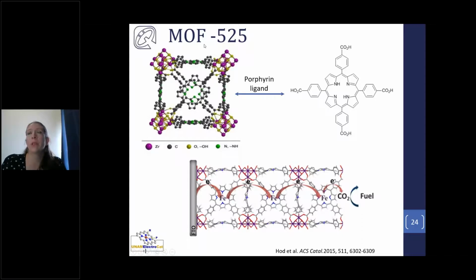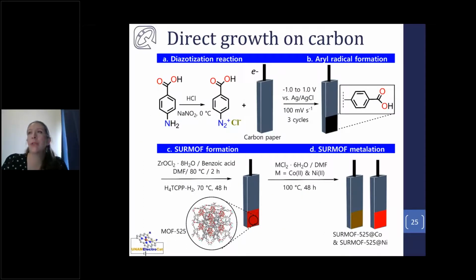One of these examples is the MOF 525, which I'm showing you here, made of a porphyrin ligand as a linker. This porphyrin ligand can be metallated, so we could generate an active site that resembles those that we believe are the active sites on our carbon material. So this is a great model system for our catalyst. And in fact, there have been some reports of this MOF metallated with iron as a good catalyst for the CO2 electrochemical reduction. So for this reason, we started focusing on preparing electrodes of this MOF to test as electrocatalysts.